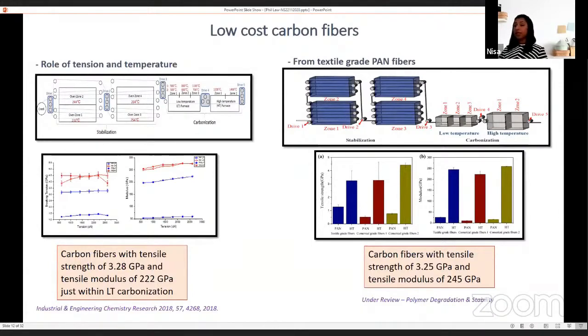In another study, instead of using the normal carbon fiber precursors, we selected textile grade PAN fibers, which is much cheaper than carbon fiber grade. And in the study, we came up with a tensile strength of 3.25 gigapascal and a modulus of 245. So this work is currently being considered for publication in Polymer Degradation and Stability.